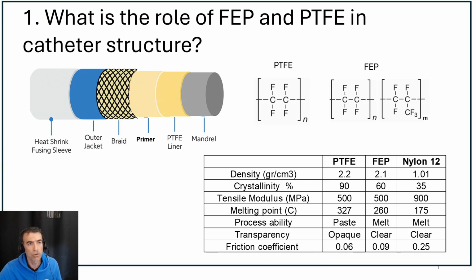But these active carbon atoms can react with the oxygen or other materials in the environment. So we use a primer. If you use a polyurethane-based primer, it would react with some diisocyanate and add diisocyanate groups on the surface, making the surface more reactive and creating functional groups on the surface. This enhances the bondability of PTFE. It would be more reactive and could bond with other materials.